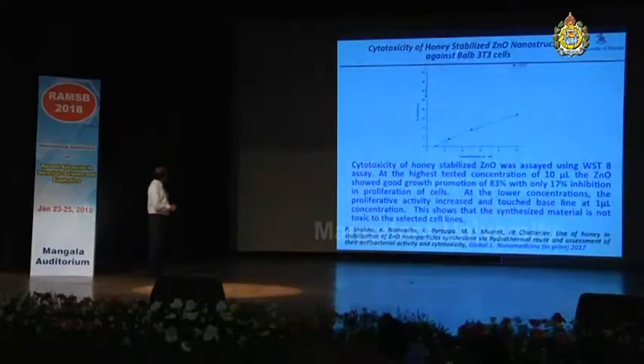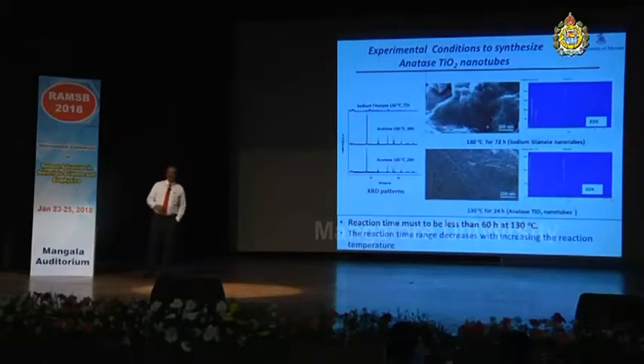The cytotoxicity of honey stabilized zinc oxide nanostructures. Again, we have tested with 3T3 cells, and these are the standard assays the biologists use, and at the highest tested concentration of about 10 microliters, the zinc oxide showed good growth promotion of 83% with only 17% inhibition in proliferation of cells. So some of these results are very encouraging for further biological studies, and I will touch upon the nanotubes which we have synthesized. In fact, some of these data are unpublished, and now they are at different stages of communication.